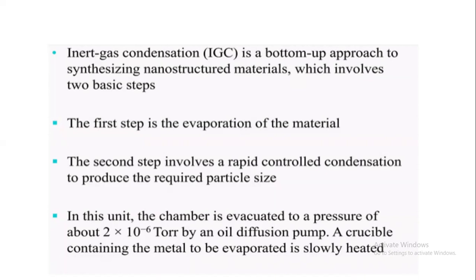In this unit, the chamber is evacuated to a pressure of 2 × 10^-6 Torr by an oil diffusion pump. A crucible containing the metal to be evaporated is slowly heated.